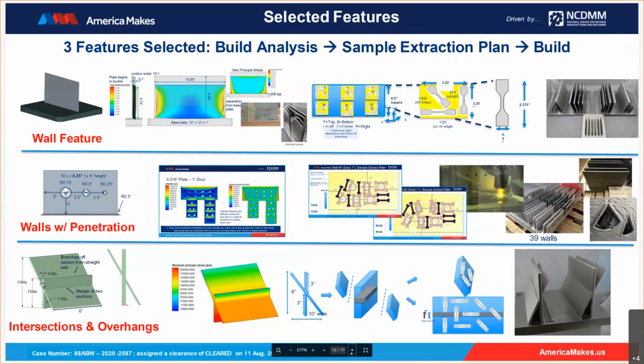While all the process performed on the wall feature is relevant for the other two, we had to also bring in other process parameters that are contextually relevant for the hole, and so the penetration and the intersection overhang features. For example, with the wall with the penetration, you have notches at the corners, you have skin effects such as upskin and downskin, and those features can influence the performance of the material. So we had to factor them into the matrix as well. Right. Next slide, please.